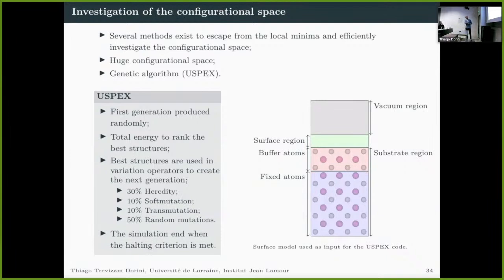There is a palladium indium substrate separated into several regions. The first one is the fixed atoms. The second one is the buffer atoms, which we allow to relax alongside the oxide. We have the surface region where we deposit the indium and oxygen atoms. And there is also the vacuum region.